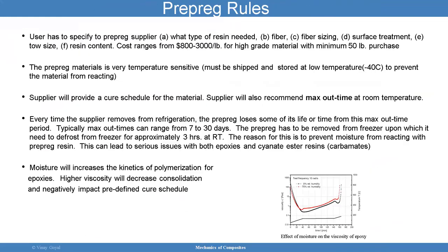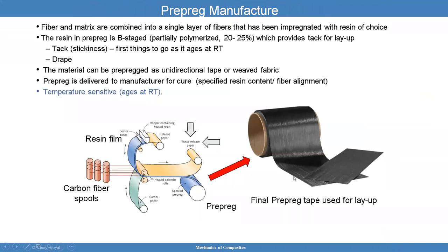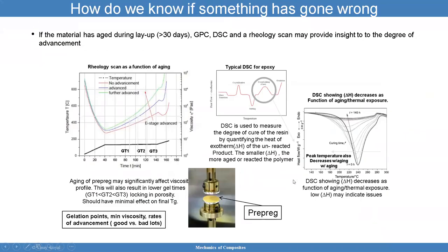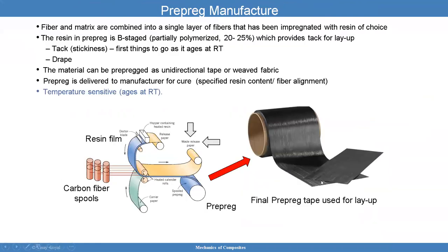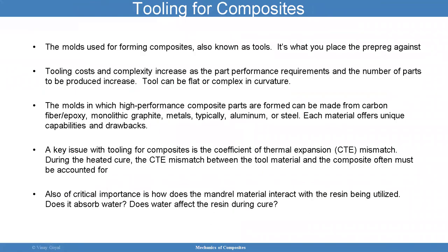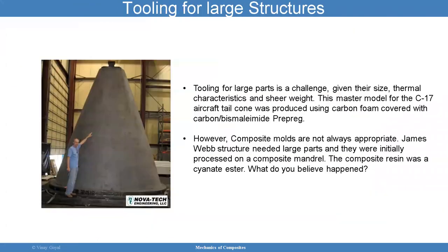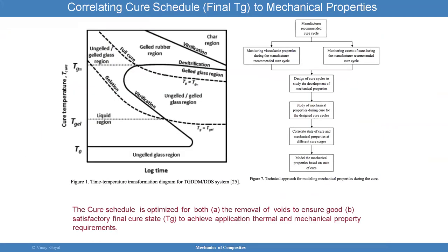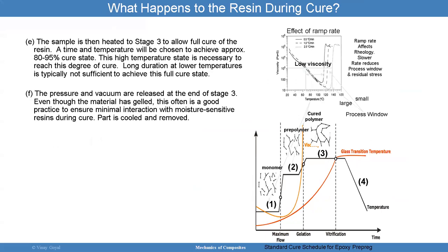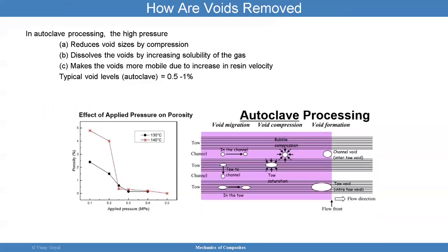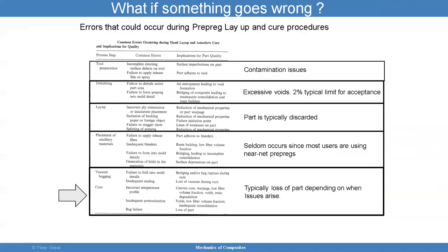So this roll here, let me see if I can find the image. This roll usually comes with a backing paper so that it does not stick on itself. We don't want this to stick on itself as it's being rolled. I'm sure all of you have experience using tape three years after you used it last time, and everything's kind of stuck, and you have to figure out how to get the tape restarted and initiated for application. Very similar concept here. We use backing paper, and sometimes backing papers can be left behind by error. Failure to stagger darts, splitting of prepreg, that can reduce mechanical properties.